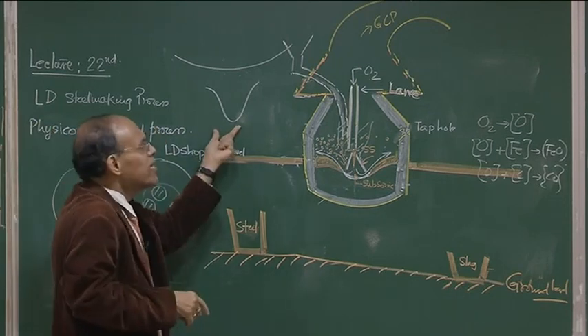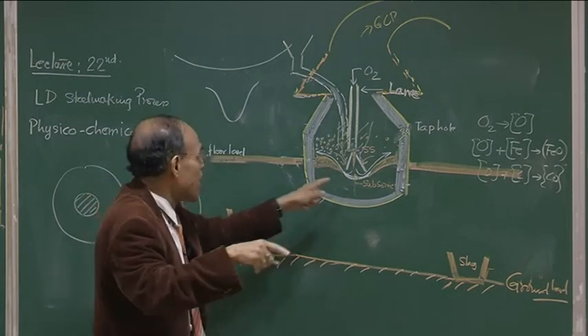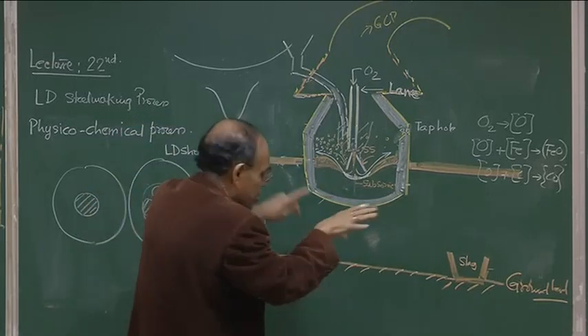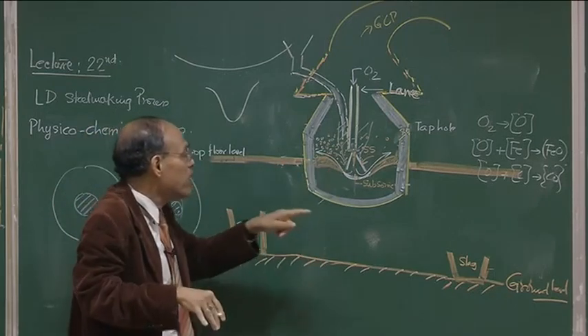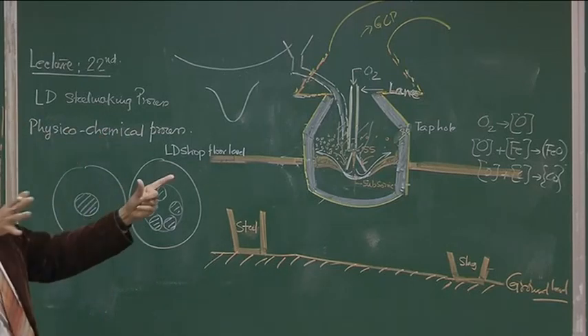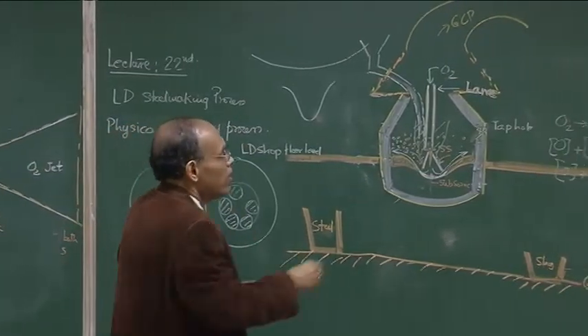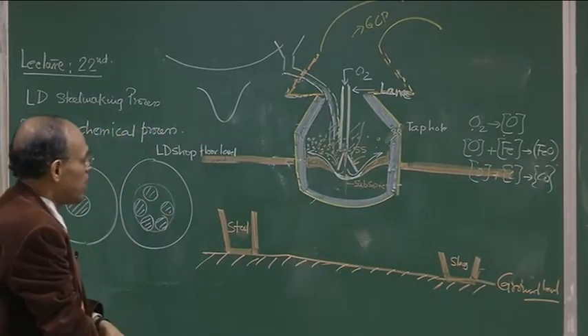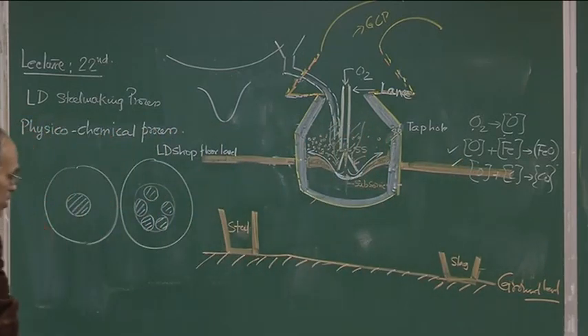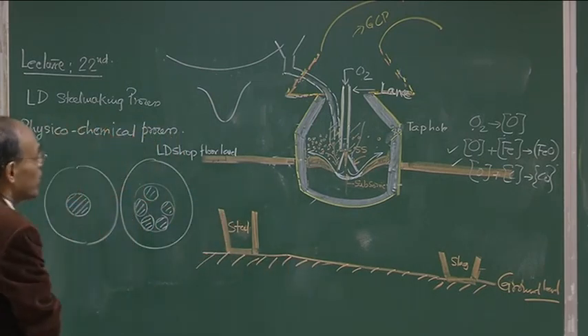And this will determine that initially, in the first minute of the blow, you have to blow it hard so that the slag separates out, when some slag has formed, FeO, SiO2, etc. Oxygen is going to be directly impinging onto the surface. So you want to cover a large area so that the gas-metal contact area increases substantially, expediting the dissolution of oxygen into the melt itself, and that will subsequently give rise to quite a bit of iron oxidation, as well as carbon oxidation, producing very large